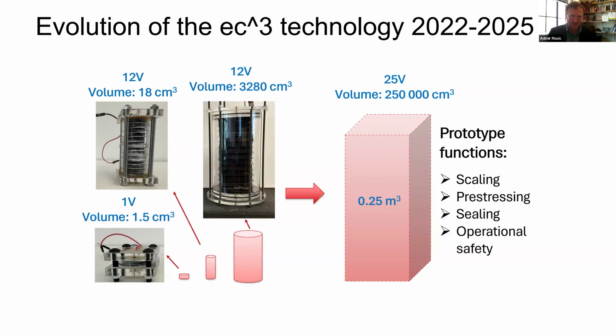And of course, when it comes to energy storage, our prototypes evolved significantly from 1.5 cubic centimeters, 1 volt single unit to 12 volts, 18 centimeter cube prototype. Then you see 3,000 cubic centimeter 12 volts unit, and then the most recent unit is a quarter of cubic meter, 25 volts prototype. And this evolution in size confirms an important theoretical outcome, that these systems are scalable. Independently from the size, you continue to maintain the performance, which is very, very important.